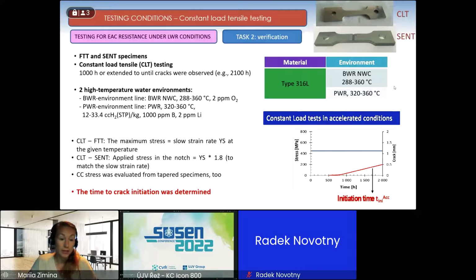Yeah, so the constant load testing for the FTT specimen was performed when the maximum stress was equal to the slow straining rate yield stress at the given temperature from the previous task. And for the SENT specimen, notched specimen, we had the applied stress in the notch, which was equal to the yield stress times 1.8, which was done to match the slow strain rate conditions. And the CC stress was also evaluated from tapered specimens in this task to increase the statistics. So the main point of this constant load tensile testing was the determination of the time to crack initiation, so initiation time.